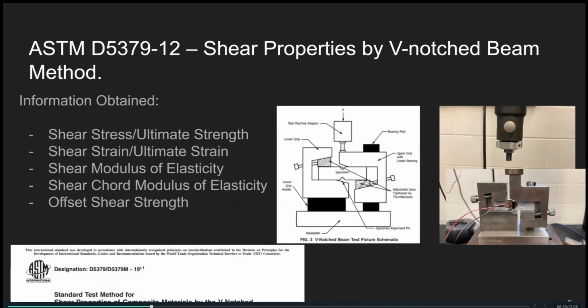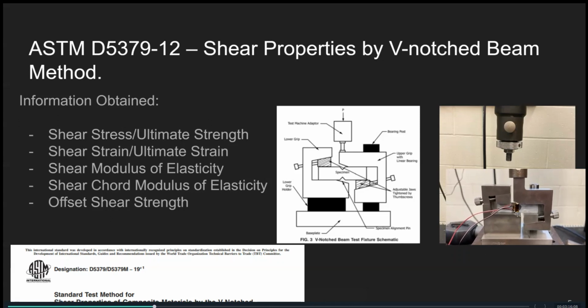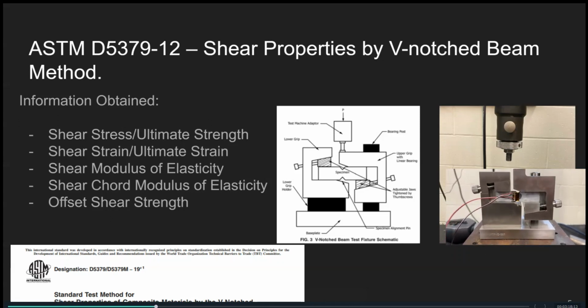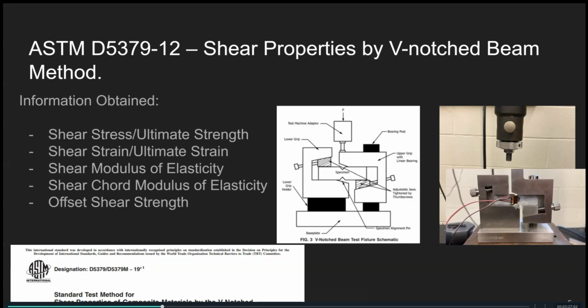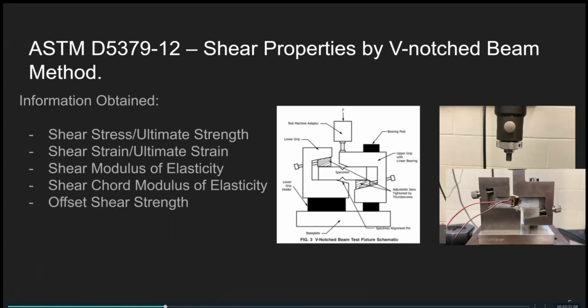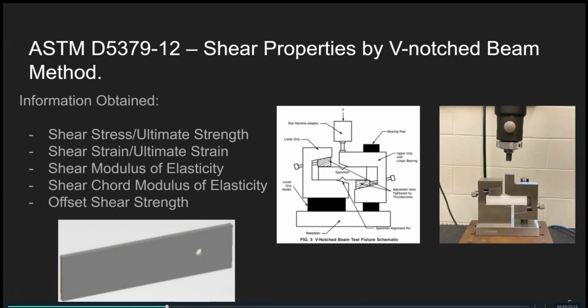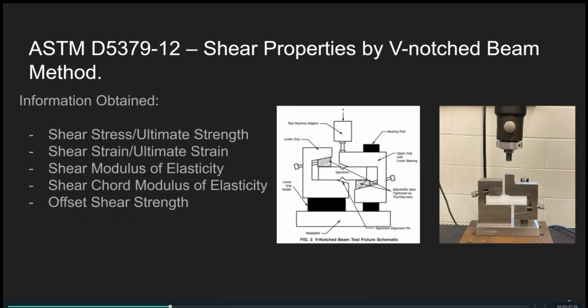We also explored shear properties. We ran ASTM D5379, which is a V-notch beam shear test with a strain gauge in the center to explore what kind of strain the specimen was experiencing. We obtained the shear stress and ultimate strength, the shear strain and ultimate strain, the modulus of elasticity, as well as the chord modulus and the offset shear strength. So we obtained that stress strain curve.